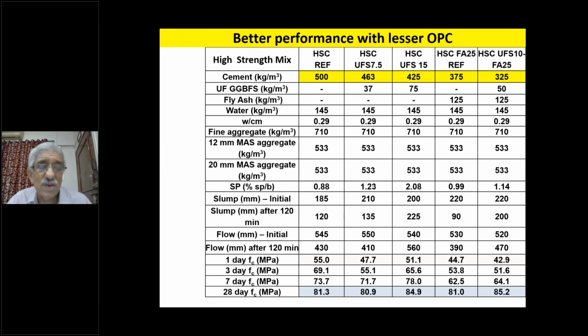I'll give you one example which we did with different mixes, and the first mix was a reference mix. Only cement was used. The second mix was using ultrafine slag 7.5%. The third mix, ultrafine slag 15%, and then ultrafine slag with fly ash. And the last one is ultrafine slag 10% with 25% fly ash. Now all of them had cement content varying from 500 to 325. This was the least, because we have used both fine and ultrafine material, and the strength was the best.